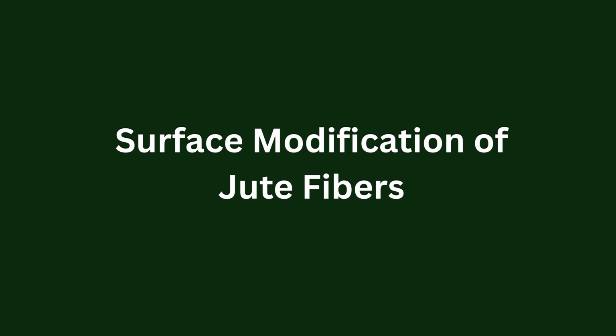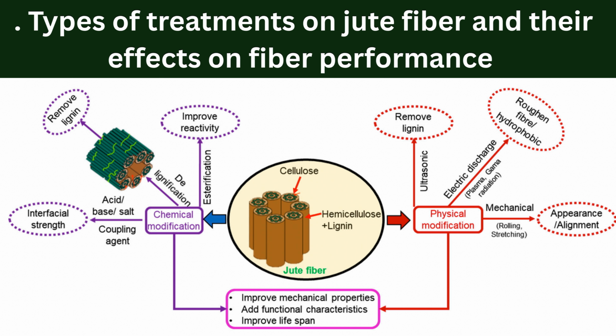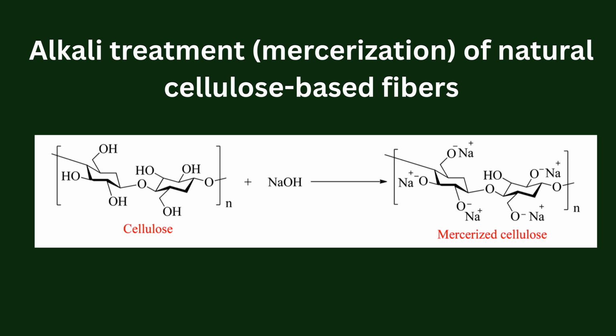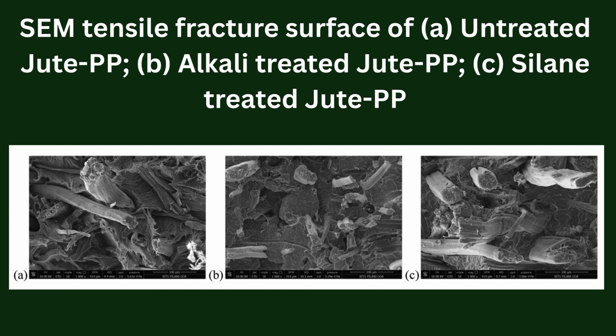Surface modification of jute fibers. A major challenge in jute composites is the poor interfacial adhesion between hydrophilic fibers and hydrophobic polymer matrices. Surface treatments are therefore essential to enhance compatibility and mechanical performance. Chemical treatments: alkali treatment, using sodium hydroxide, potassium hydroxide, or lithium hydroxide, is the most widely used method. It removes hemicellulose, lignin, waxes, and surface impurities, resulting in increased surface roughness, reduced fiber diameter, up to 8%, improved tensile strength, up to 44%, and enhanced fiber-matrix adhesion. Silane coupling agents and maleic anhydride grafted polymers, for example MAPP in polypropylene systems, further improve chemical bonding at the interface.